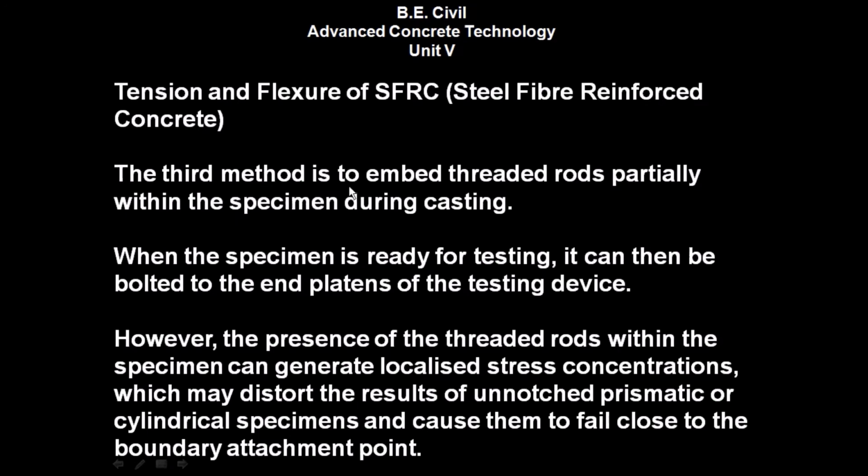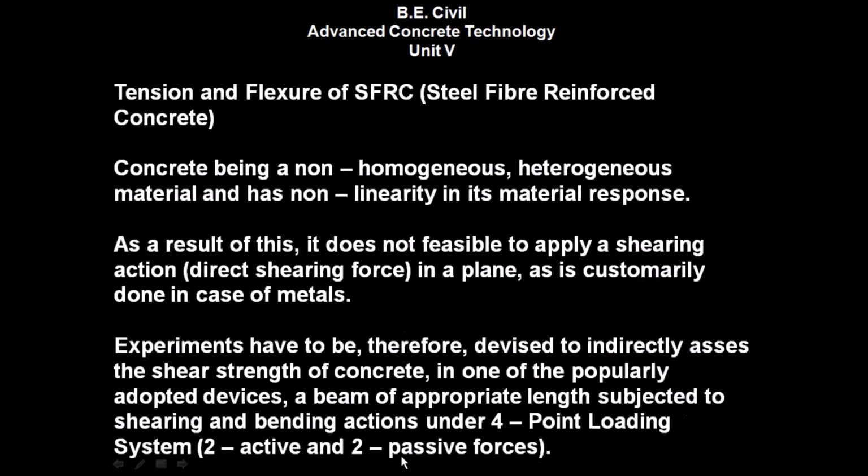The third method is to embed a threaded rod partially within the specimen during casting. When the specimen is ready for testing, it can then be bolted to the end platens of the testing device. However, the presence of the threaded rods within the specimen can generate localized stress concentrations which may distort the result of an unnotched prismatic or cylindrical specimen and cause them to fail close to the boundary attachment point.